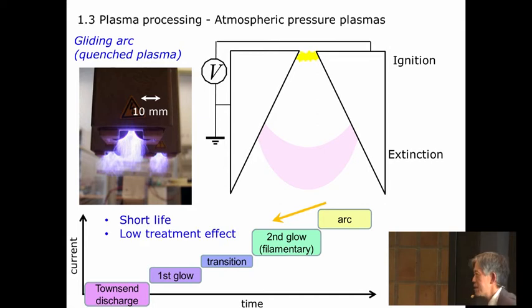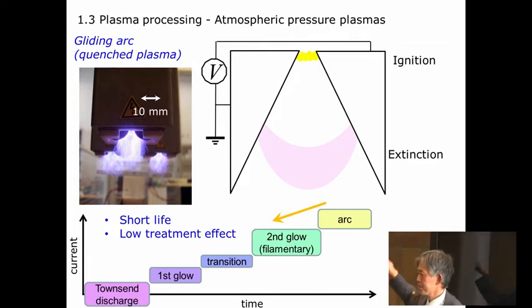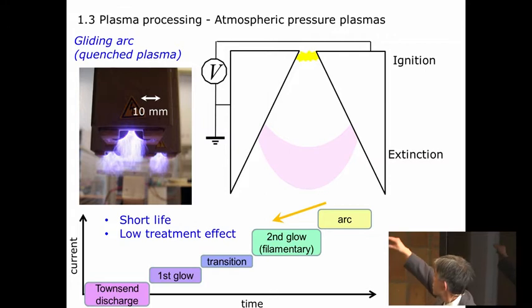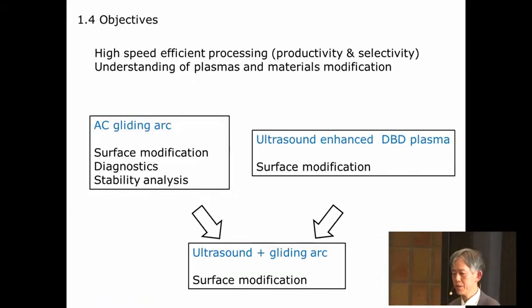But in reality, especially in my previous experience with commercial gliding arcs, the lifetime of the non-equilibrium plasma is relatively short. The extension of the plasma is quite short, and also typically it has a low treatment effect. But because of this kind of very interesting potential, I wanted to tackle it and find a solution for nicer performance of the gliding arc. That's a kind of motivation, and so I'm already talking about something about that. So the essential motivation was to have higher speed, efficient treatment of the plasma devices.